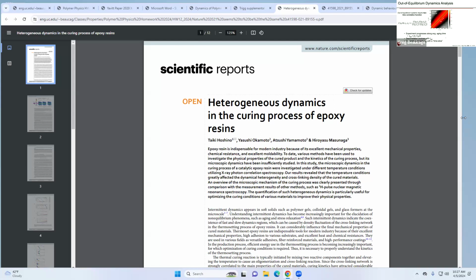Okay, so bear with me. The really interesting part about this research is this out-of-equilibrium nature. What that means is that the dynamics and the structure of our material is changing on the timescale of our experiment. So we can't just do one of these XPCS experiments and get the relaxation time. The relaxation time is changing as we're taking data. The way we observe that is on these two-dimensional plots, which are called two-time correlation functions. Instead of doing a correlation function from just the first frame across all the other frames, we do correlations at every frame in between. So we create basically a 2D matrix where we're comparing all the data that we have across all times. Again, that took me a really long time to get my mind around as well, but it makes sense in this 2D picture.